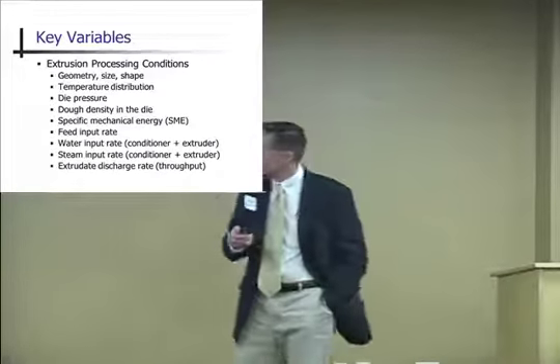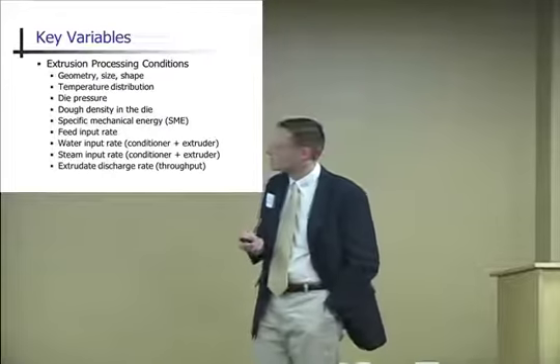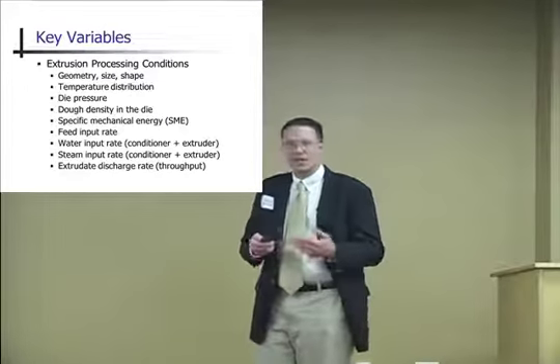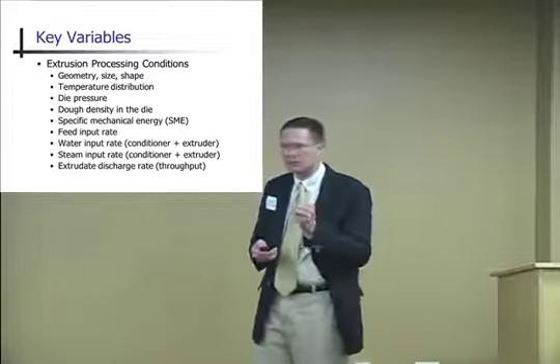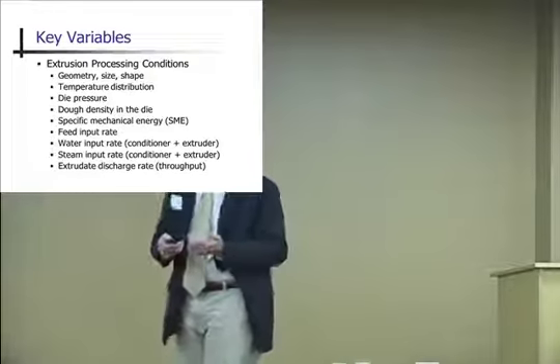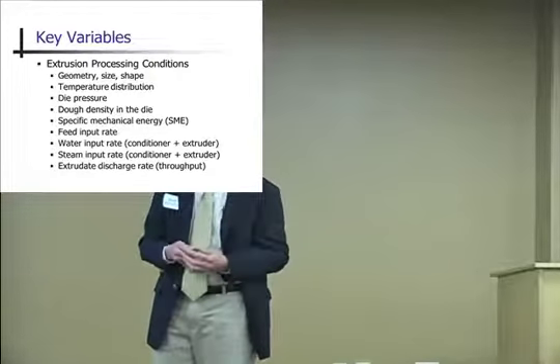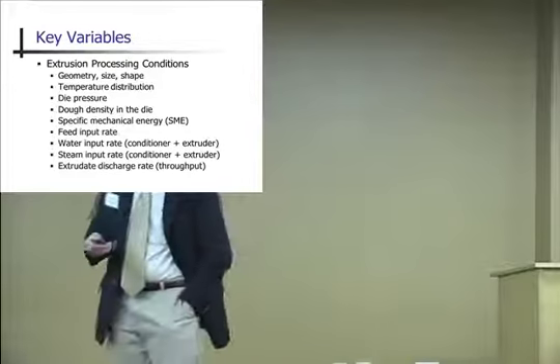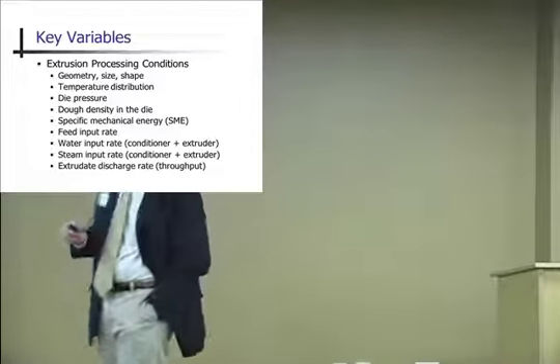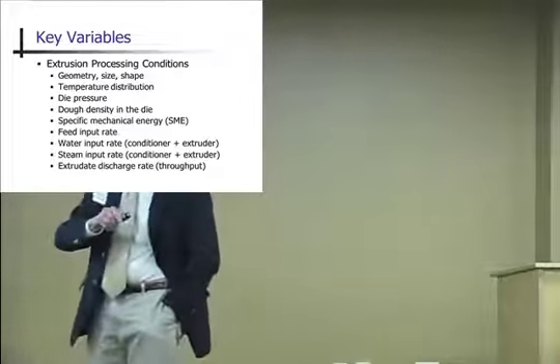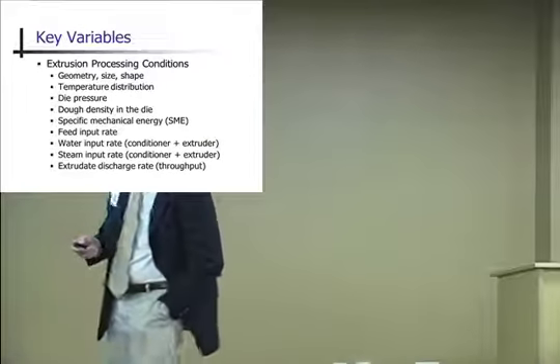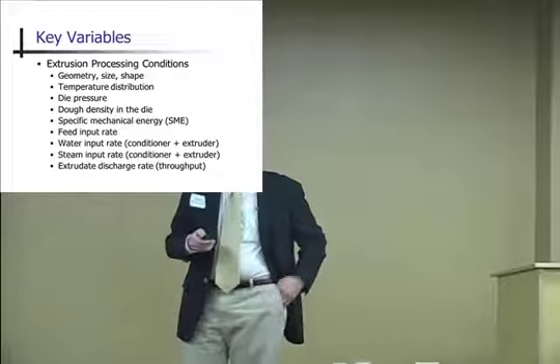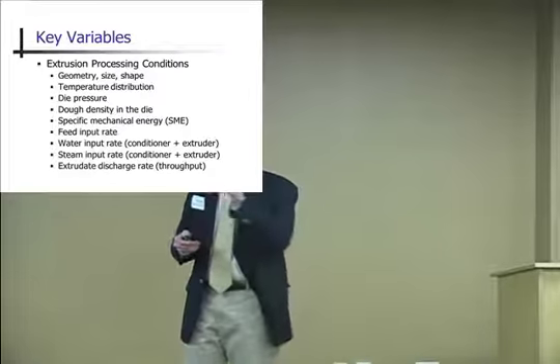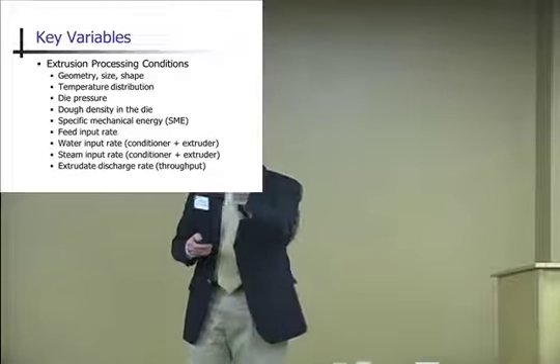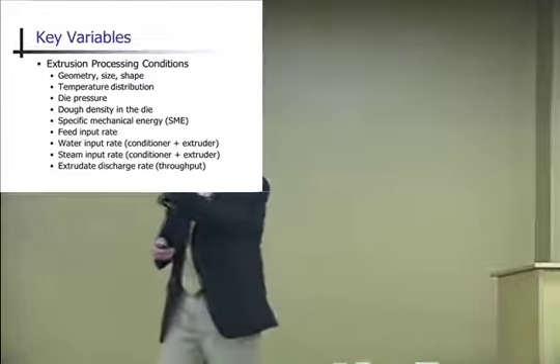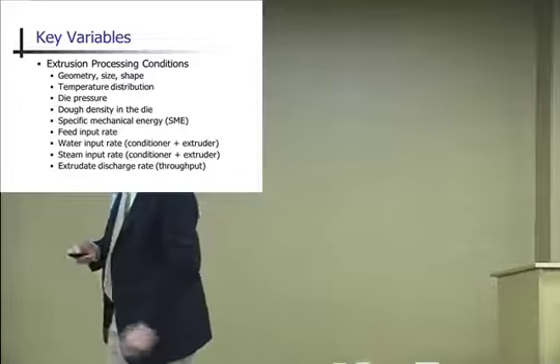So when we look at the extrusion processing conditions, the size, the shape, the geometry of the pellet is important. The distribution of temperature through the extruder is important. Die pressure basically defines how much expansion you get as that pellet comes out of the die. Then the viscosity and the density of that dough as it's exiting the die. Basically, it's a liquid that's coming through that die right before it expands. So we need to be able to control that.